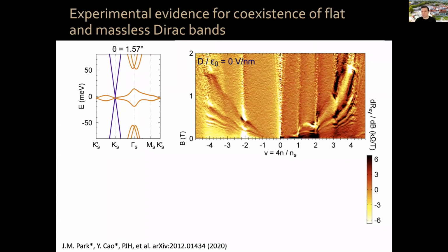And what you can see is that at each integer, we have a vertical feature, okay? Those are the equivalent of the insulator or semi-metal states for the magic angle twisted bilayer graphene-like part of the electronic structure. And then on top of that, we have this sort of parabola. This is not really a parabola. What you are seeing is the Landau fan diagram of the monolayer graphene-like part. This is the Landau levels. All of these traces are the Landau levels of the monolayer-like part.